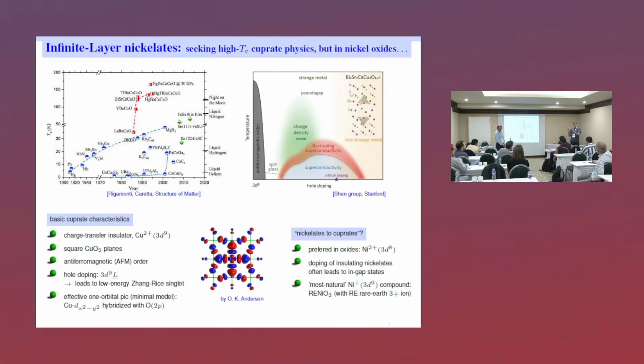And in the nickelates, this problem just jumps in your face, because there things are similar in the sense that the role of oxygen is very subtle and crucial, but one cannot so easily put it under the rug, at least from my point of view. And again, as you said, the role of oxygen is not so important in the sense that it's not of charge transfer kind, so the holes do not want to go to oxygen. That is true. It's still important in setting the energy scales and the hybridizations. And then it's different from the cuprates, where we have this strong linking.